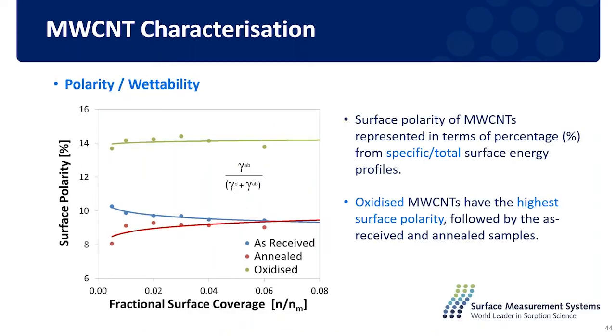And the polarity of the carbon nanotube could be calculated from the specific component of surface energy over the total component of surface energy. And here it also shows the oxidized sample has the higher polarity, which also indicates it's more hydrophilic in nature compared to the other samples, which is as expected with the additional introduction of the oxygen groups.